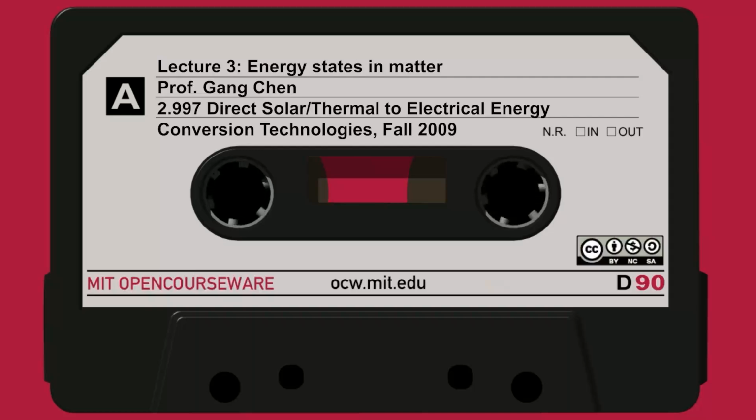If one can solve that problem through some method, you solve a huge problem. Even in the microscopic world, it's energy conservation and momentum conservation, whether you learn it in the continuum or in the discrete. That's always true. So silicon doesn't absorb well, gallium arsenide absorbs well.